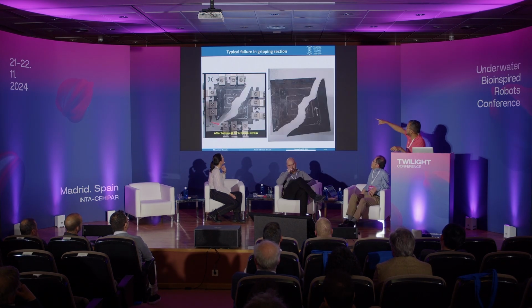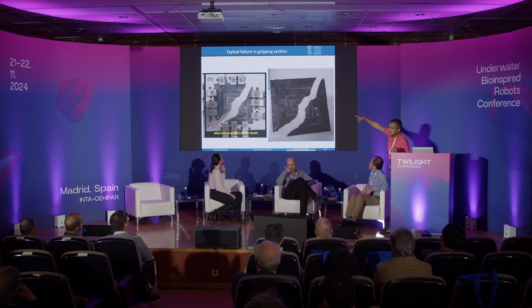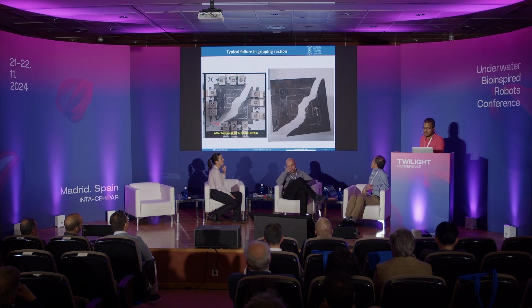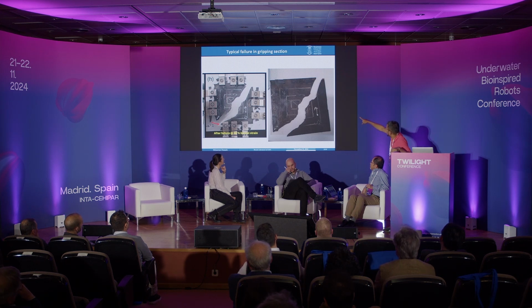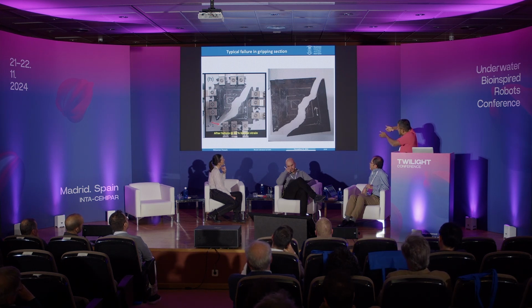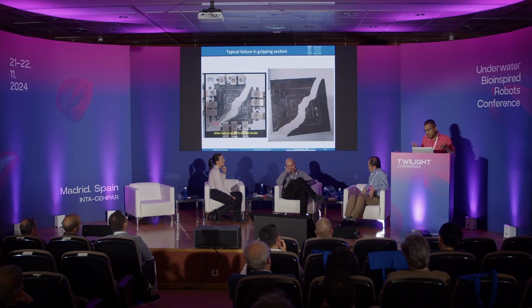So we found the fatigue start, or the crack start, at the gripping section, diagonally, in some of the gripping sections. Then one way is to make the gripper, I'm not sure I have this photo or not, but I did not put it here. So then we put some glue, and then we made the S a little bit thicker, but still the problem is there.